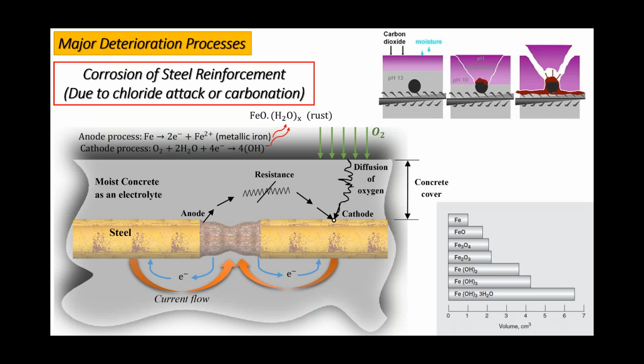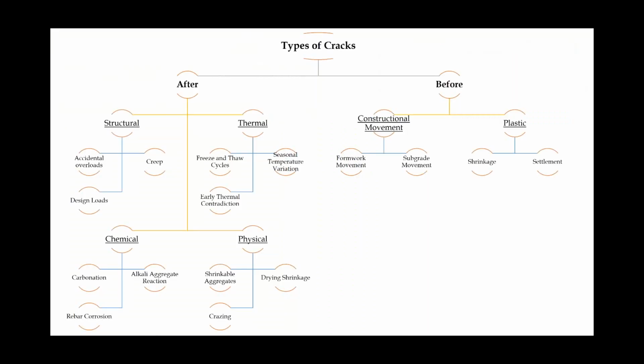Similar items, because when we have the different forms of oxidation states in the iron, the photo on the right-hand side shows the volume is also expanding by 6 times, which again is going to induce pressure to the concrete wall, and we may have cracks. Why am I mentioning cracks so many times? We have different types of cracks inside the concrete. So the cracks can come before